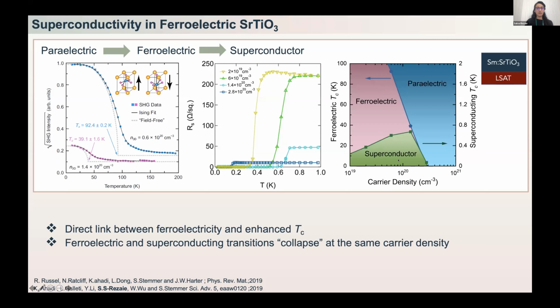The peak of superconductivity, very similar to the bulk strontium titanate that I mentioned, happens around 10 to 20 per centimeter cubed. But this time, you can see that the superconducting critical temperature is enhanced, almost double what we would get from bulk strontium titanate. So we wanted to realize what is special in this connection between ferroelectricity and superconductivity, where we can still get the superconducting dome, but the dome has now been shifted to higher temperatures.